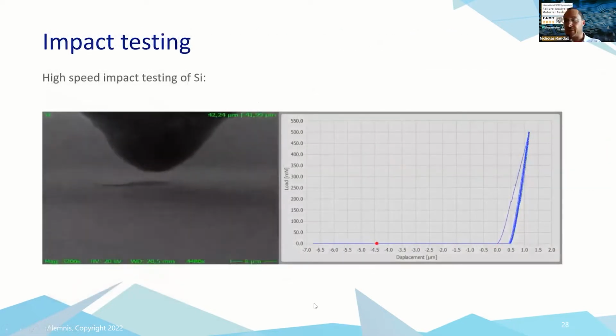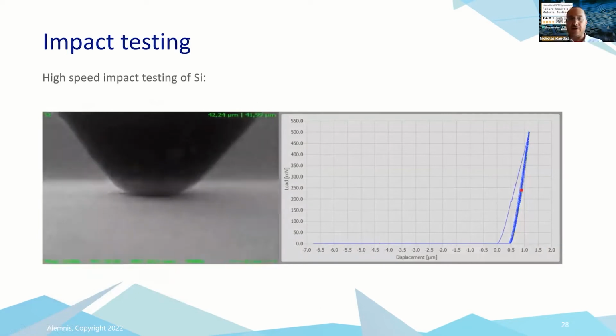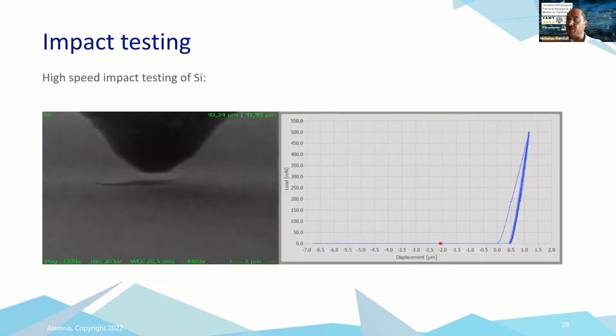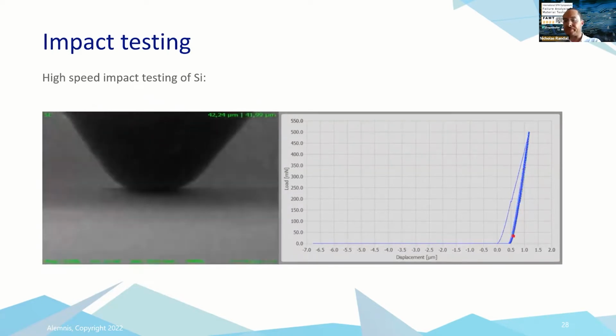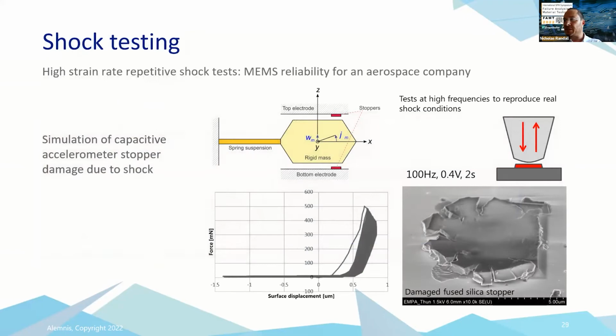We can also do impact testing, as I mentioned before. This is simple impact on a silicon wafer, just so you can see how cracks propagate in the material. This is an example of using impact for shock testing. So this is an accelerometer, capacitive accelerometer. So we're basically simulating the suspended accelerometer part hitting the stoppers. And so we're basically repeatedly hitting the stopper and seeing how many cycles it takes to fail that material.